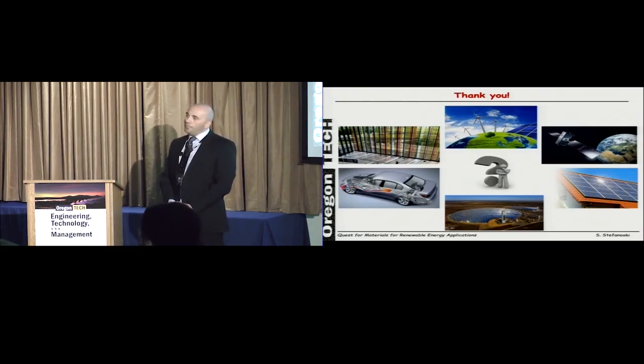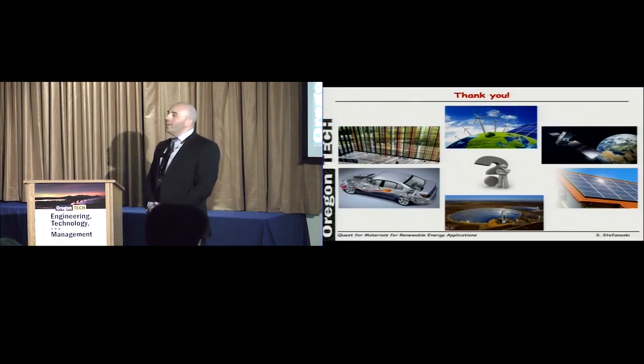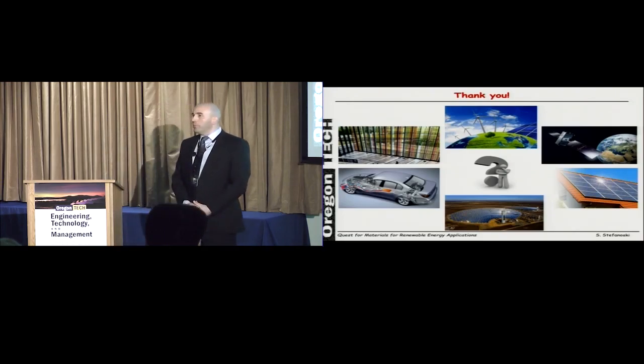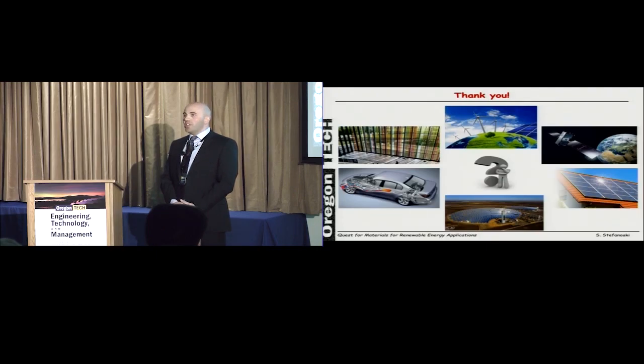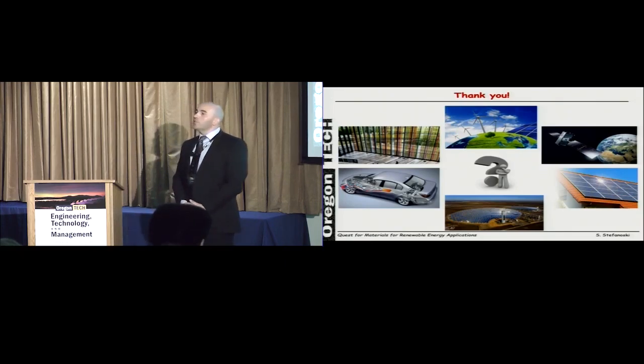How will the efficiency compare to current solar panels? That's a good question. So our conservative estimate at the moment, based on the absorption properties we have, is that we would expect solar panels with efficiencies of about 35%, while the current state of the art for bulk materials, not thin film, is about, let's say, 25. So that's a pretty decent increase in efficiency.